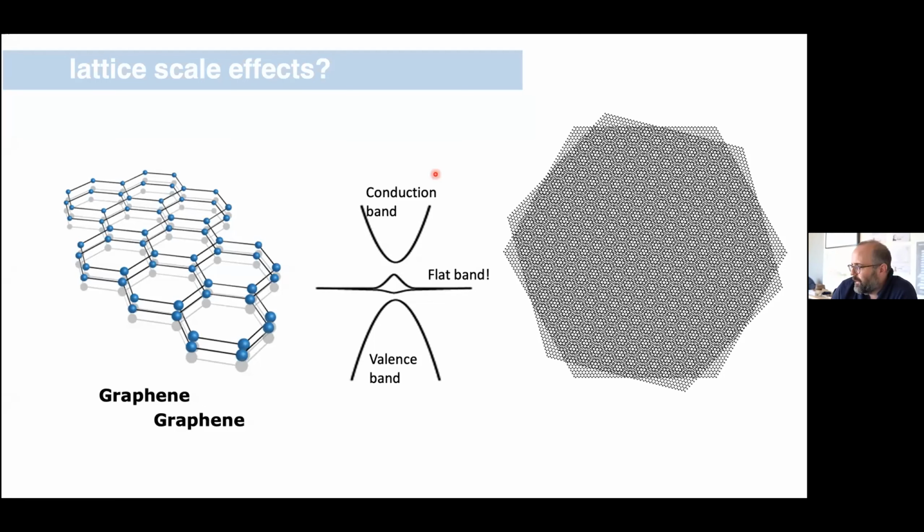So that's really interesting, as was said before, because if you can get yourself into a situation where Coulomb energy exceeds kinetic energy, then the properties that such materials can have can become even more interesting than the native class of materials that we discussed before. Whether something is a metal or a semiconductor or an insulator is what we call a single particle character. Each individual electron behaves as if it's in a system that is one of those three. When Coulomb energy starts to dominate, then new correlated phases can emerge. That can be things like superconductivity or interesting magnetic order or interesting correlated insulating states, interaction-driven insulating states, etc.